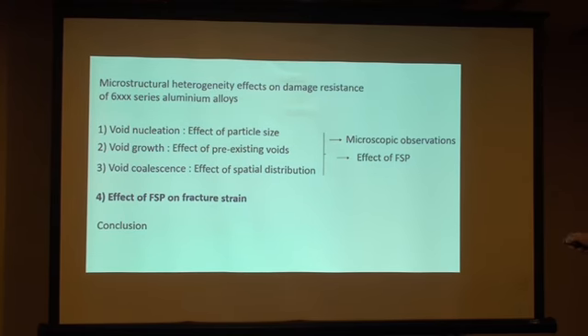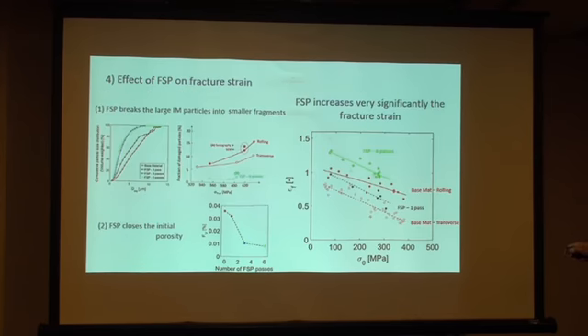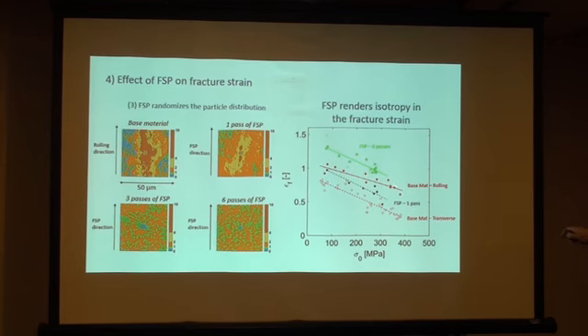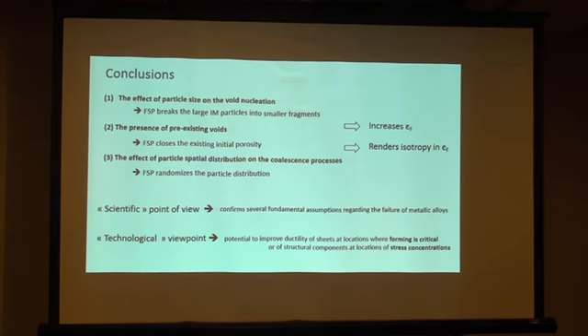With this effect, we have reduced the particle size, so we decrease the nucleation. We have suppressed existing voids, so of course this increases the ductility. And I would like also to show that we have suppressed the anisotropy of the fracture strain. So just the results. As you can see, this is the initial void volume fraction as a function of the number of friction stir processing passes. It decreased a lot, and the nucleation has decreased. After 6 passes, you see that there is almost a 50% increase in ductility. And also, because we have randomized the distribution after friction stir processing, trust me, there is no more anisotropy in the fracture strain. And with this, I would like to say thank you.